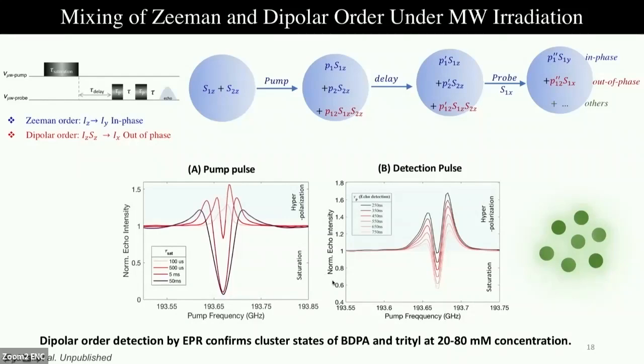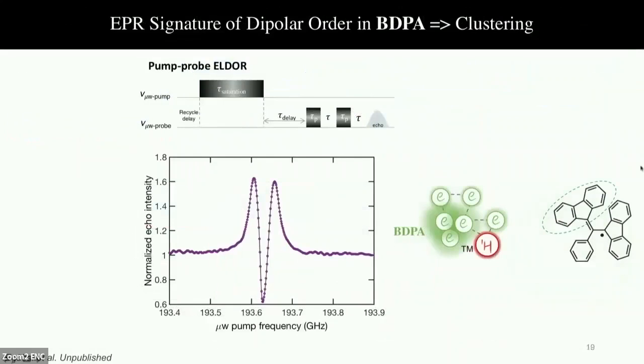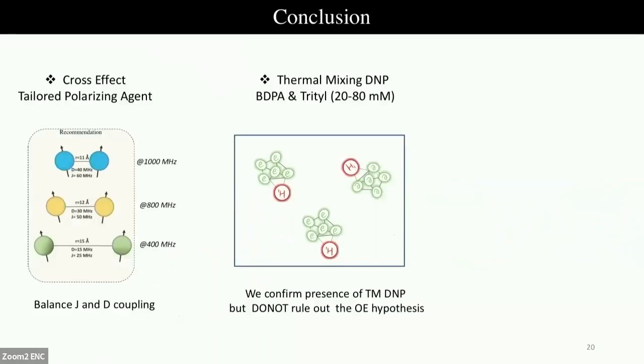So these experiments show that the state of the electron spins is in fact a clustered state in the case of Trityl, and something which we also see in BDPA, which gave rise to, in our opinion, thermal mixing DNP, where we have these strong humps coming up in the BDPA EPR experiments. It could be because in BDPA, we have these biphenyl rings, which could lead to stacking of different BDPA molecules. So with that, I would like to conclude.